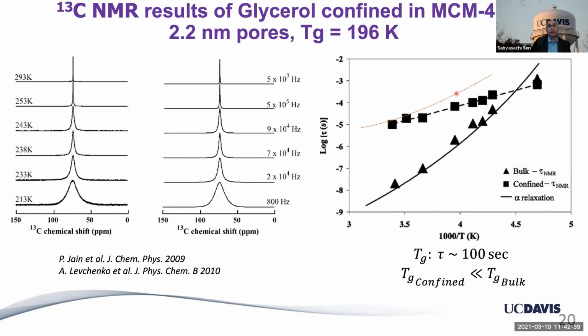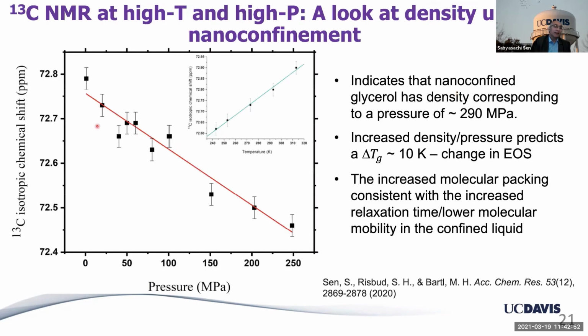And again, NMR chemical shift can come in handy there, because for glycerol we have found out that the NMR chemical shift depends on the volume or the density of the liquid. And here is a plot of pressure dependence. We did high pressure NMR on glycerol, and this is the pressure dependence of the isotropic chemical shift, and this is the temperature dependence in the inset.